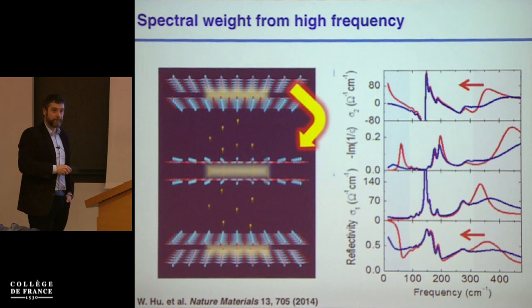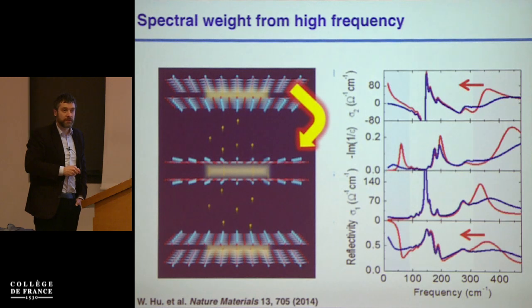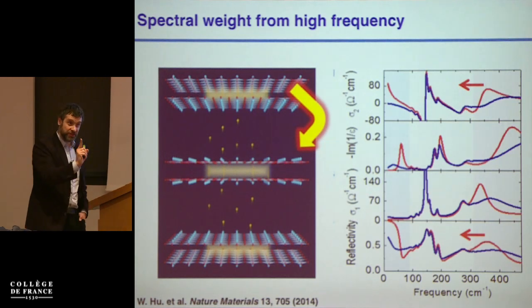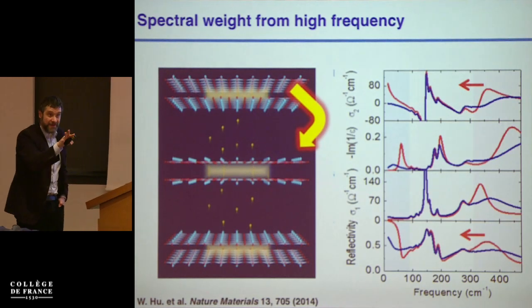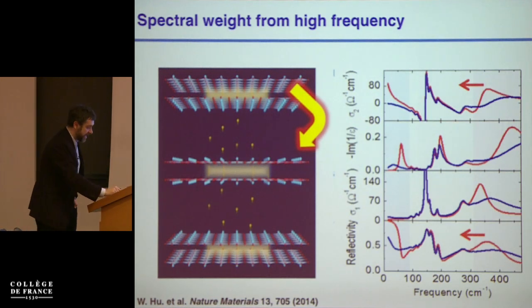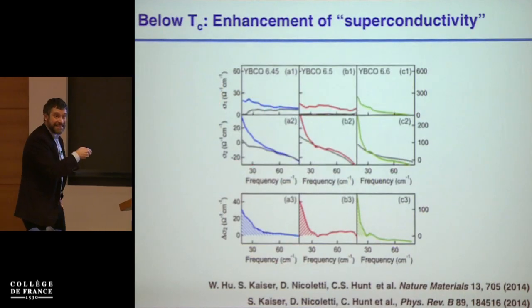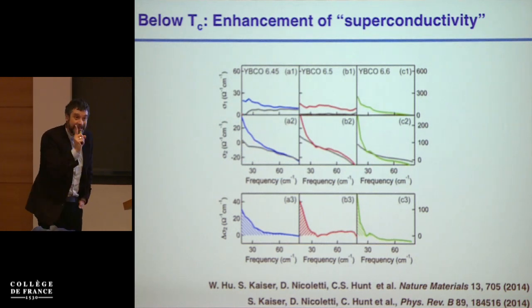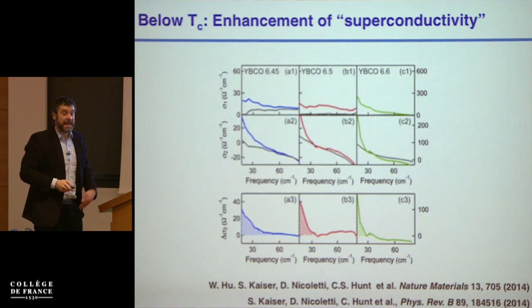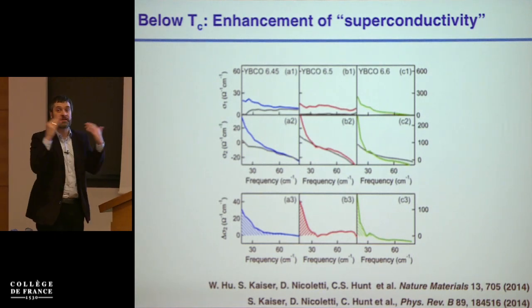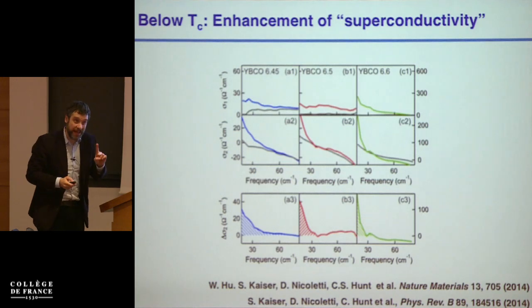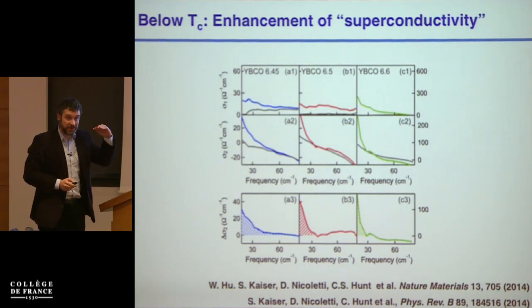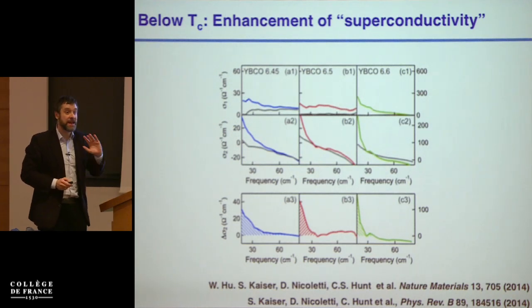Yes? So the sigma is measured along the z direction? Yes, yes. In principle, if you were to measure along the in plane, you would expect something similar, no? So this is exactly the question. This is right on the money, so I should have explained this better. In principle, what you could say is the following. The fact that I see that the Cooper pair tunneling becomes stronger perpendicular to the planes can be a consequence of the fact that the total number of Cooper pairs is getting larger. If that were the case, you would expect the in-plane sigma 2 to go higher, exactly as you say. Okay? This is, by the way, not what happens. I'm not showing you the data.